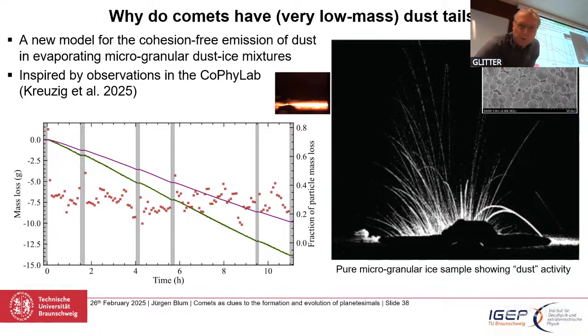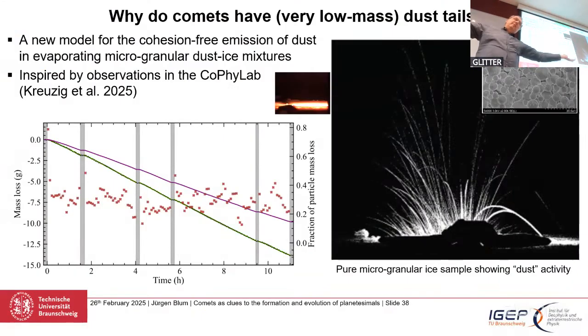And what we're seeing, I show you a video first, and then I discuss the picture, is that if you shine some artificial light on it, mimicking the sun, you occasionally see particles flying off. It's dust active. There is no dust in it. It must be ice particles. There's nothing else in it. It's just ice. So we switch the lamp on, it becomes active, we switch it off, it's inactive, we switch it on again. It goes on forever and ever. We did that over many, many hours. You see how the dust comes out exactly where the sun shines in, bringing energy and heat, of course. And we measured the mass of the sample as it reduced, and calculated the mass as it should reduce by measuring the surface temperature by evaporation.